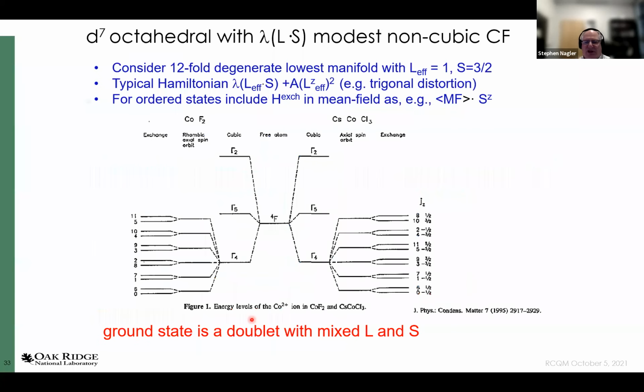And if I think about what happens then, sort of typically in these cobalt 2+ systems, you'll also have a departure from a perfectly cubic octahedron and some spin orbit coupling. Those tend to be of sort of the same, if you like, order of magnitude. And if I think of spin 3/2, L equals 1, that's a 12-fold degenerate lowest lying manifold.